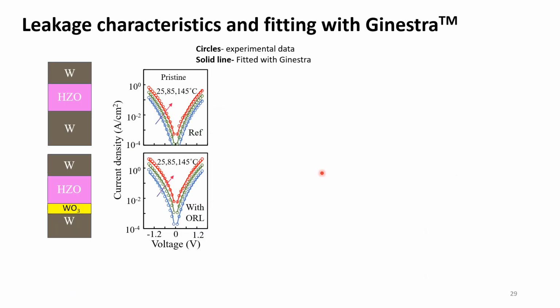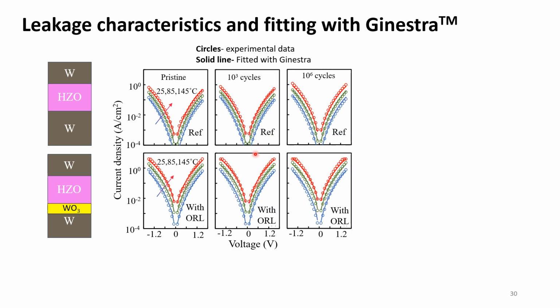So for that study, we have measured the leakage current for both the devices. You can see the top plot is coming from the reference device and the bottom plot is coming from the tungsten oxide or the ORL device. Each plot has multiple curves here. These are coming from the measurements done at 25, 85 and 145 degrees Celsius. These plots are coming from the pristine device, and we did the same measurements after 10 to the power 3 and after 10 to the power 6 cycles.